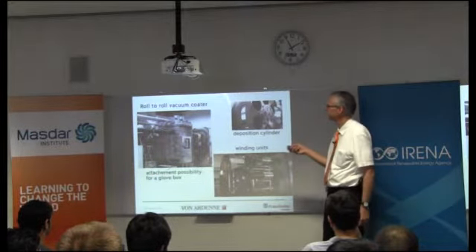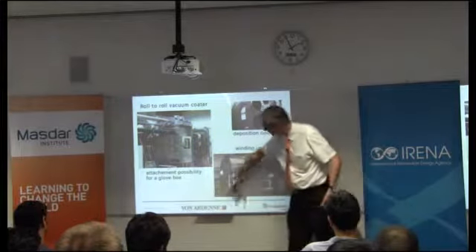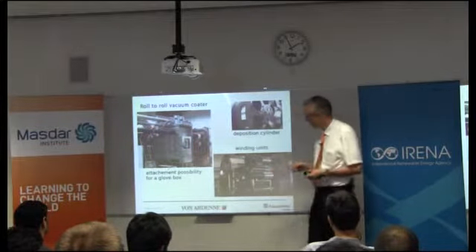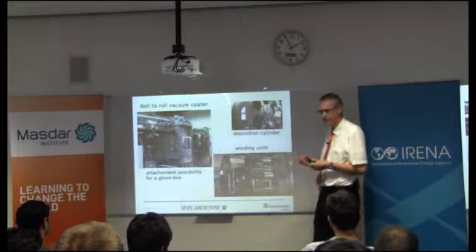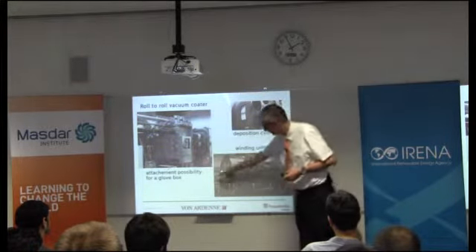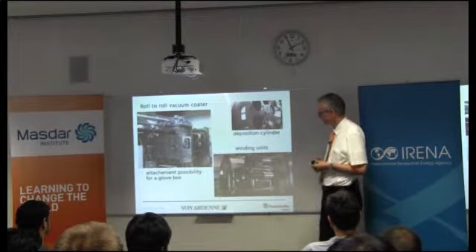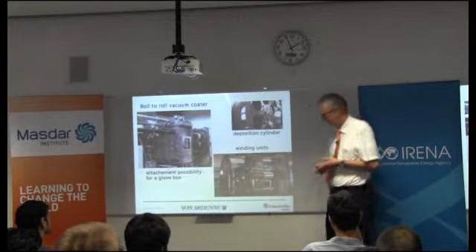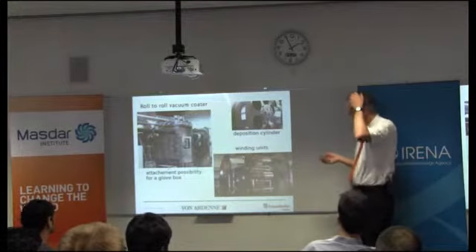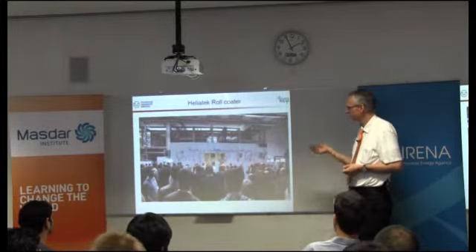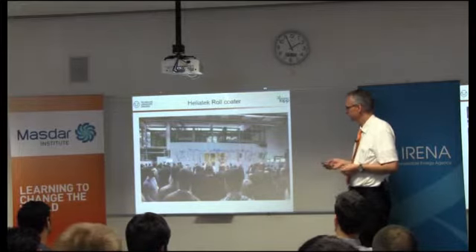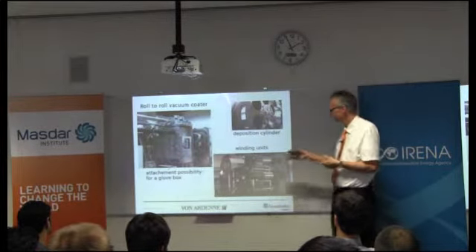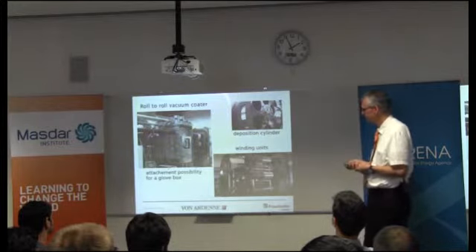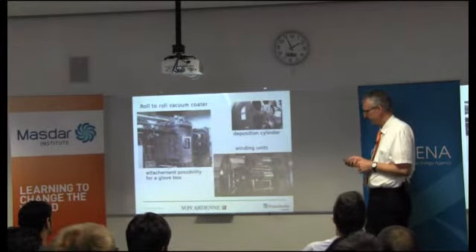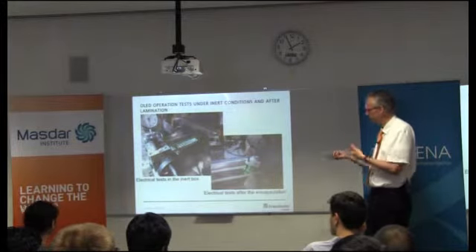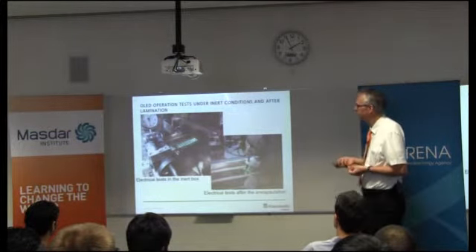And what you cannot really see here is around these cylinders you have the evaporation sources, and if you have a sequence of 12 layers you only need 12 sources, and then you pull it once through and all the 12 layers are on the substrate. And this works actually surprisingly well, and this tool from Heliatek here is now operating and producing pilot material, and therefore it is possible to do this complicated multi-layer system in a very efficient way.